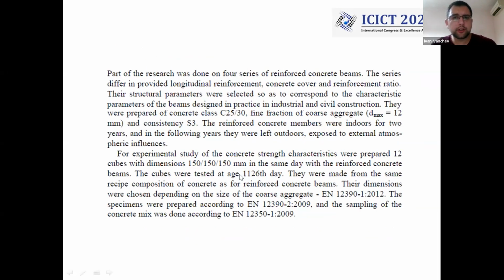So about the research, part of the research was done on the 12 reinforced concrete beams. They are situated in 4 series. In the different series we have a variation in the provided longitudinal reinforcement, concrete cover, and reinforcement ratio. I may tell that the used concrete is of grade or concrete class C25/30. We have a fine fraction of the coarse aggregate and consistency S3. About the cubes, we use 12 cubes with dimensions 150, 150, and 150 millimeters.